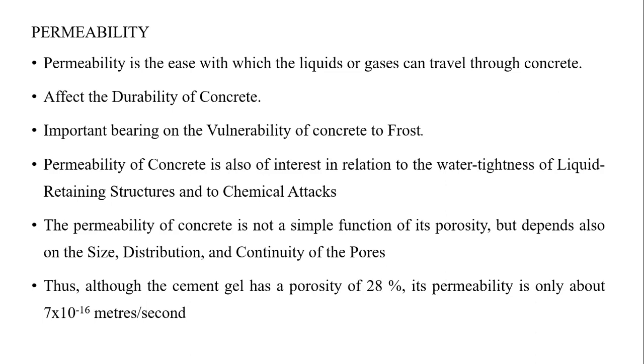Important bearing on vulnerability of concrete to frost. Permeability of concrete is also of interest in relation to water tightness of liquid-retaining structures and to chemical attack. The permeability of concrete is not a simple function of its porosity, but depends on the size, distribution, and continuity of the pores. Thus, although cement gel has a porosity of 28%, its permeability is only about 7 times 10 to the power minus 16 metres per second.